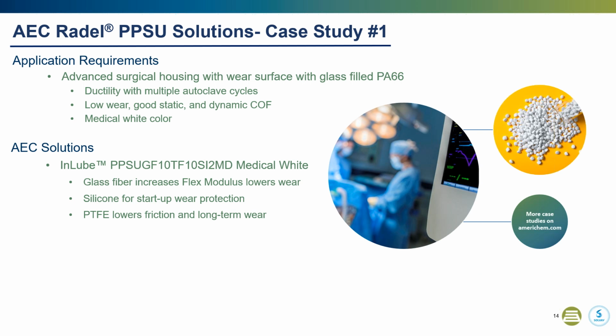It's important to keep flex modulus of mating materials close to each other, as wear starts when one material flexes and starts deforming. The 10% glass fiber was added to raise the flex modulus to 550,000, since the lubricated only TF10 SI2 lowered the Radel's flex mod to 320,000. None of these additives created a challenge to create the white or any color.